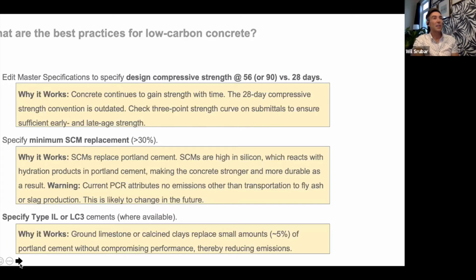Number 2 here is to specify a minimum supplementary cementitious materials replacement. This really gets at replacing part of Portland cement, a minimum threshold of that. And I already explained that there are a bunch of benefits of doing this. One thing that I will note is that, right now, if we look at the embodied carbon calculations for concrete, the product category rule, how we attribute the emissions of fly ash and slag, are such that we don't account for previous emissions associated with coal combustion to get the fly ash or steel making to get the slag. The only thing that we account for is transportation.